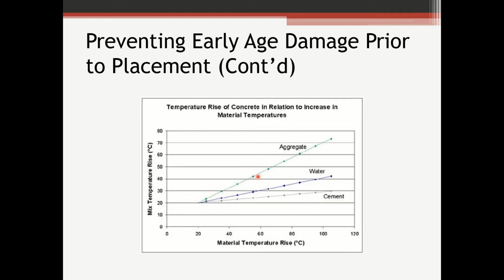You can see the slope of this curve is a little bit steeper for the aggregate. Heating up your aggregate is going to give you a lot more bang for your buck. For every 2 degrees of temperature rise in your aggregate, you'll get maybe about a 1 degree temperature rise in the overall mixed temperature.